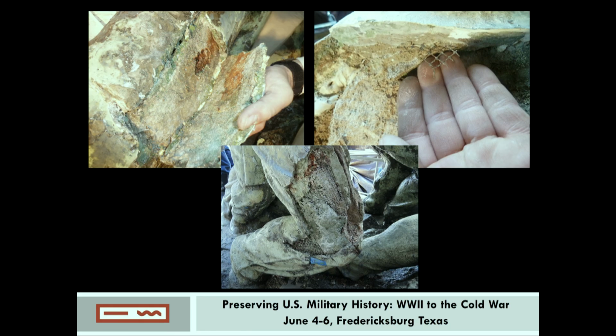The sculpture appears to have been fabricated by packing clay around a welded steel reinforcing system to which the prefabricated concrete shell was attached. A green pigmented mortar was then packed around the clay and rebar system. And you can see that in the slide here. Galvanized steel mesh was placed on top of this layer, and then another layer of green mortar. The concrete shell was then attached to the rebar and clay form.